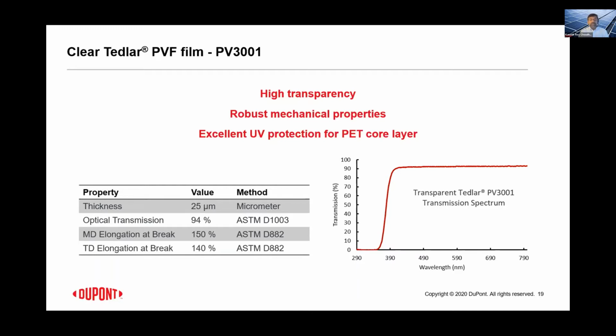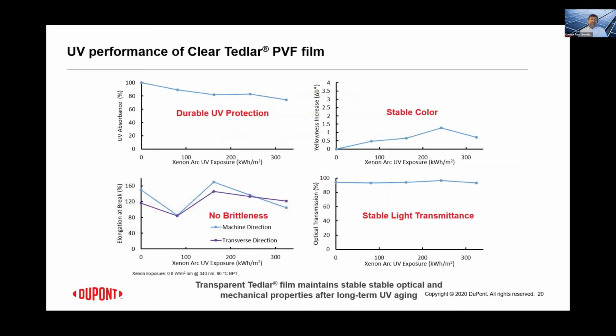Here are some numbers just from the initial measurements of the material. It's a 25 micron film, very competitive optical transmission versus the incumbent, which is glass in this area. The other thing that I'm showing here is the optical transmission is pretty much flat across the entire spectrum, which is important. And then I'll come back to this, the MD and TD elongation. These refer to basically the mechanical properties of the film.